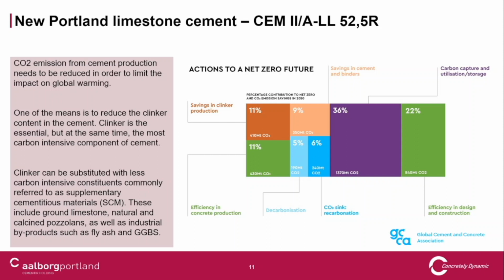Then savings in clinker production, meaning, for instance, shifting to biogas instead of fossil fuel, could help reduce our CO2 footprint from clinker production. But here, 9% of the CO2 savings needs to come from cement and binders. That means we need to produce cement with less clinker, which has a lower CO2 footprint—not because of the clinker itself, but because of the substitution of the clinker. That's what we're doing with the new limestone cement: taking out approximately 15% of the clinker and replacing it with limestone.